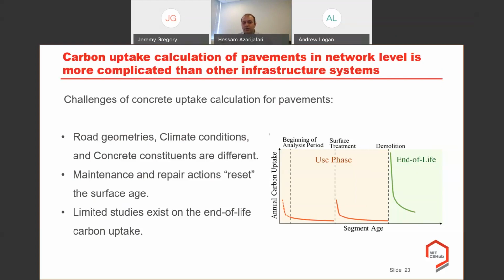The second one is the maintenance and repair actions. Once we apply maintenance and repair actions on concrete pavements, we are removing a part of the concrete by, for example, diamond grinding a thin layer, which will remove the carbonated layer. Or we put a concrete overlay on top of the previously built one. Therefore, the age of the surface will become 0 again. So as you can see, when the surface treatment is applied, schematically here, we have a small carbonation rate. And when the age becomes 0 again, meaning that we are applying a diamond grinding, the carbonation will start accelerating again and will continue following the Fick's diffusion law.